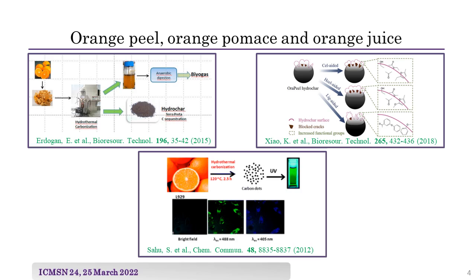In a later work, orange peel waste was treated by hydrothermal carbonization and then mixed with lignin, cellulose, and hemicellulose to modify the quantity and properties of the resulting hydrochar. It was shown that cellulose and hemicellulose increased the density of microspheres on the surface of hydrochars, and a maximum specific surface area of about 27 square meters per gram was found for lignin-added hydrochar. To the best of our knowledge, the hydrothermal carbonization of orange juice was performed only to synthesize carbon quantum dots.